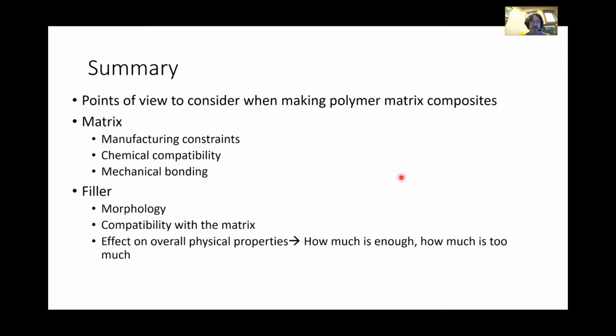So in summary, here are points of view to consider when making polymer matrix composites. From the matrix side: manufacturing constraints, chemical compatibility, and mechanical bonding - though that could go more into the filler side too, you can look at it either way. From the filler side: filler morphology, compatibility with the matrix, and the effect on overall physical properties. How much is enough? How much is too much? If you saw the tin bismuth experiments, 10% by weight was too much, but 5% was pretty much Goldilocks - it actually improved the strength.